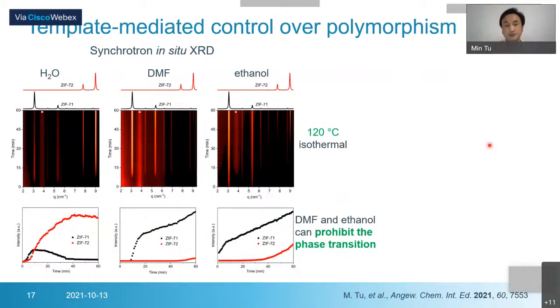So we also did synchrotron in situ XRD. We see that when we use water as an additive, water cannot avoid this phase transition. It first forms ZIF71, then it slowly disappears, and ZIF72 forms. And when we use DMF and ethanol, we can see ZIF71 quickly formed, and ZIF72 starts to form very slowly, in this case around 45 minutes. But without any additive, it quickly transforms to ZIF72.